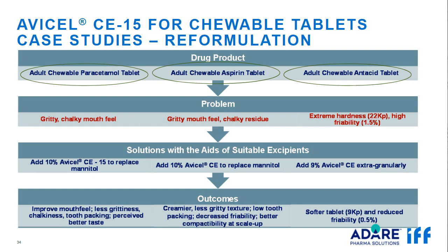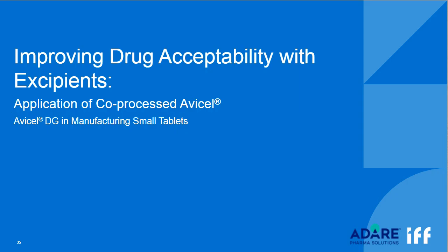In the third case study, the problem was extreme hardness and high friability of chewable antacid tablets. To optimize the hardness and reduce the friability, 9% Avicel CE was added, which easily solved the problem. Another example for improving drug acceptability using high functionality excipient is Avicel DG. Avicel DG is a co-processed excipient containing 75% microcrystalline cellulose and 25% anhydrous dibasic calcium phosphate that produces high-quality tablets, particularly in dry granulation, where we need to use material with high compactability and high reworkability.